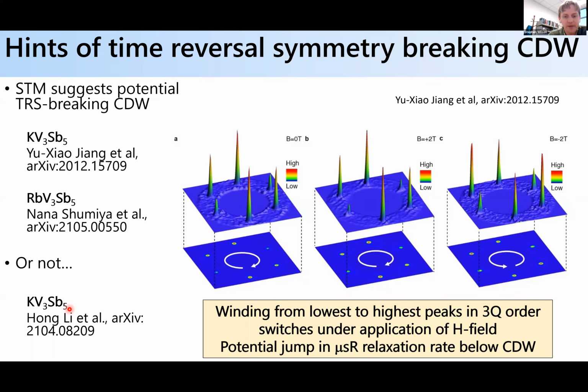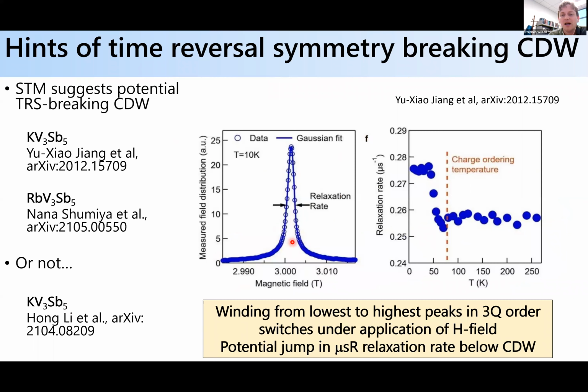Okay, so as another kind of hint that there might be some time reversal symmetry breaking below the CDW, in the same paper from Zahid Hasan's group on the potassium system, they also looked at μSR, and I think they looked at transverse relaxation rates. And so it's a very subtle effect. So basically, as they cool down, they can see a jump in the transverse relaxation rate under magnetic field, obviously, because they're applying, sorry, I want to say this correctly. It's relaxation rate under transverse magnetic field.